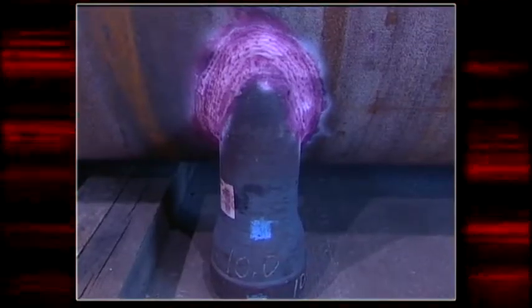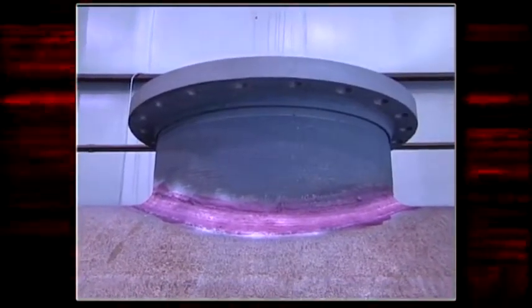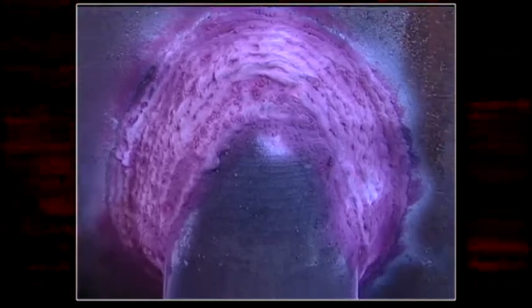U.S. Pipe is revolutionizing the industry with a new process for manufacturing welded outlets. It's all happening right here at the pipe fabrication shop in Bessemer, Alabama, and it's sure to save contractors time and money. As the name implies, these outlets are welded right into the parent pipe. Seems simple enough, right? Not so fast. Ductile iron is a fairly unique material, and it actually changes its microstructure when exposed to large amounts of heat. It's generally not a good thing. It'll greatly reduce the strength of the ductile iron. We've developed a new welding process where we are able to put smaller fillets onto our welds and reduce that heat input into the ductile iron, so we end up with a stronger product.